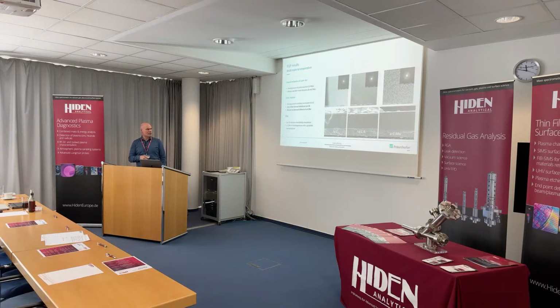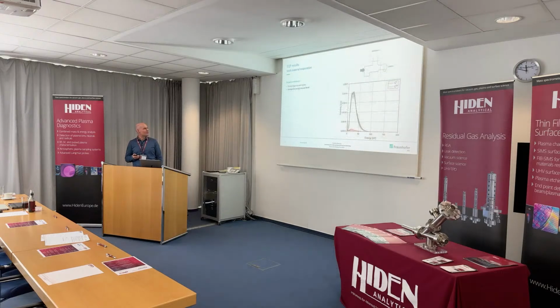And if you look at the molybdenum one, you also see a smooth surface, and you see no defects in it anymore. And the differences in the selected area diffraction you see up here in these pictures: the carbon TAC is always amorphous, the TACB stays amorphous, and in the AC molybdenum we see some graphitic nanostructure. We can also use this kind of structure for several applications, but I will come to this later. But here we have some effect of the heavy molybdenum, and I will show you some results of this on the next slides now.